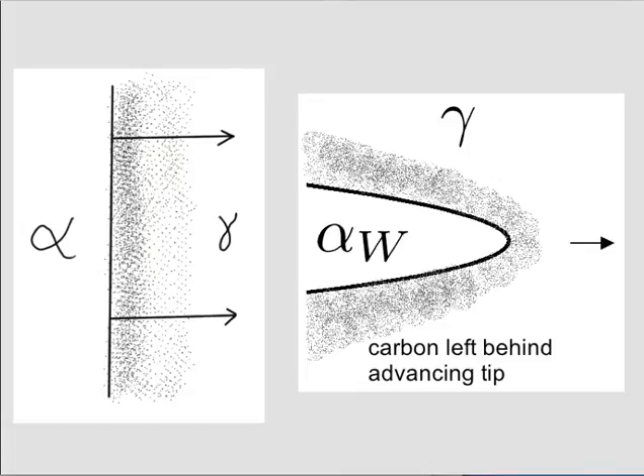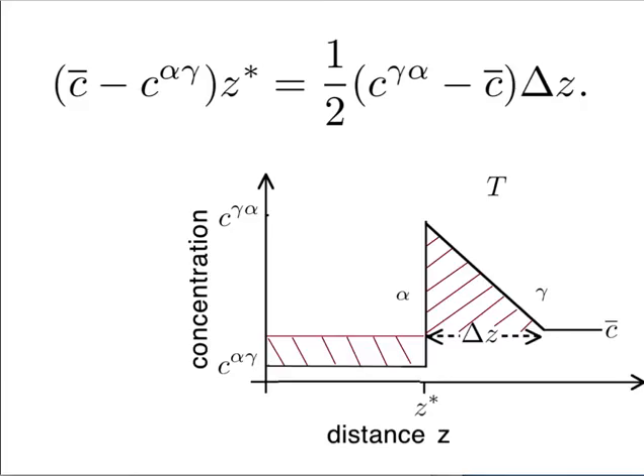The thickening of the plate will be parabolic - as we will show shortly for the thickening of the layer of ferrite. It is the lengthening rate which is constant. In the case of a layer of ferrite, everything is accumulating in front of the interface, so the diffusion distance will grow as more ferrite forms because you are partitioning more and more carbon into the austenite.